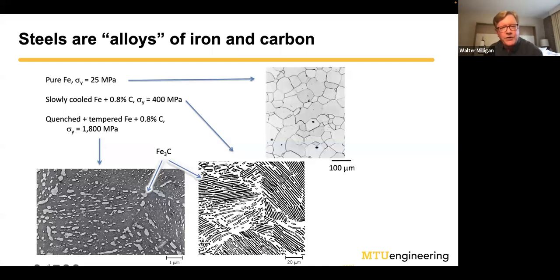If I take iron and throw some carbon in there, these two steels down here have 0.8% carbon. This is the composition of piano wire. The interesting thing about these two materials is that in both cases, we heated the material up red hot, just like the person at the forge and the people at New West Knife Works. The difference between the two is the cooling rate. This one was cooled relatively slowly. This one was cooled much more quickly, quenched in oil or in water, and then tempered. I'll explain what tempering is later.